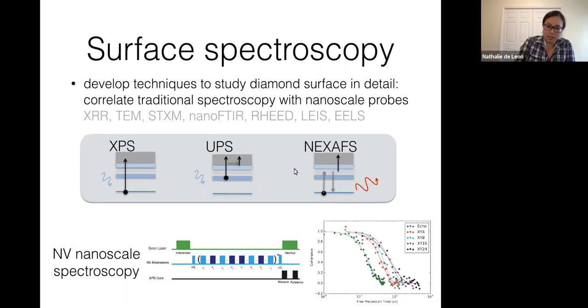In addition to these surface sensitive probes, we can do something a little bit more sophisticated than just asking the NV center whether or not it's happy, which is driving the NV center with different pulse sequences to try to learn something about the spectrum of the noise bath. So for example, you can do these different dynamical decoupling sequences that push out the NV coherence, and then you can just do a Fourier transform of that to get a spectral decomposition of the noise.